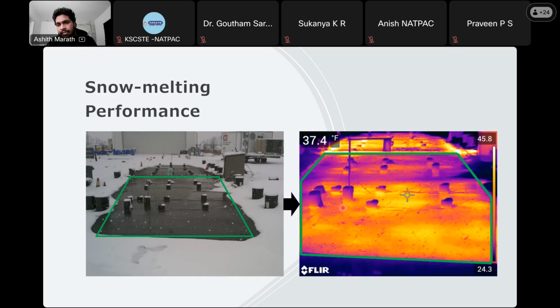And the right side shows the infrared image of the pavement surface. As you can see here, there is a gradient, right? On this portion, you can see a much higher temperature compared to this area. The reason is that these are two different electrically conductive pavements, I mean two different design configurations. And at the end, what you see is the conventional pavement. We have a conventional pavement here as well.